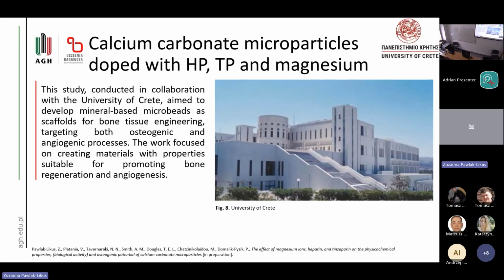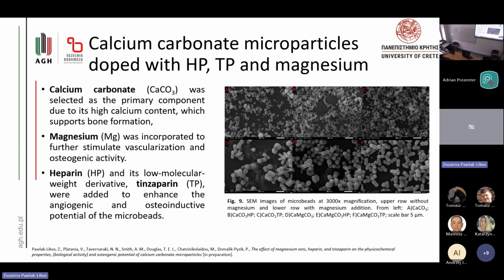Our next project was conducted in collaboration with University of Crete, which we can see in the photo. Those results focused on mineral-based biomaterials that aim to design calcium carbonate microparticles for bone tissue engineering applications that should target both osteogenic and angiogenic processes. We chose calcium carbonate as a primary component because of its high calcium content, which supports bone formation, because as we know, bone consists mainly of calcium. The additives that we used were also heparin and its low molecular weight derivative tinzaparin, because as we knew from our previous research, they can support angiogenesis and they have some osteoinductive potential.